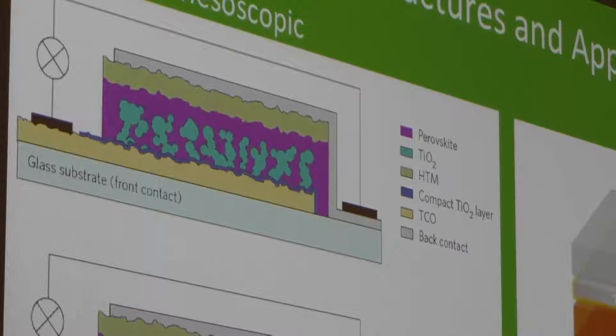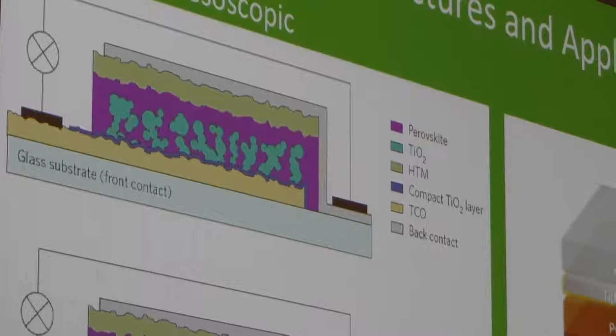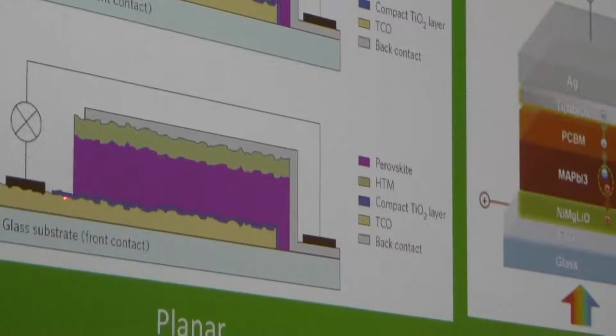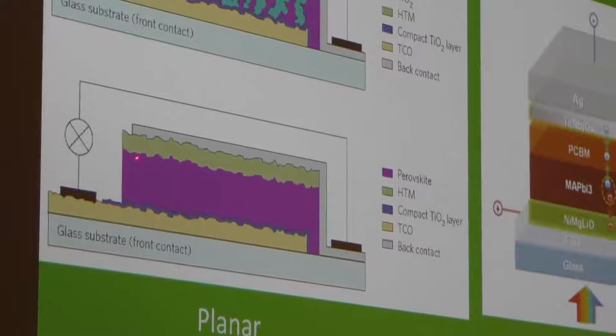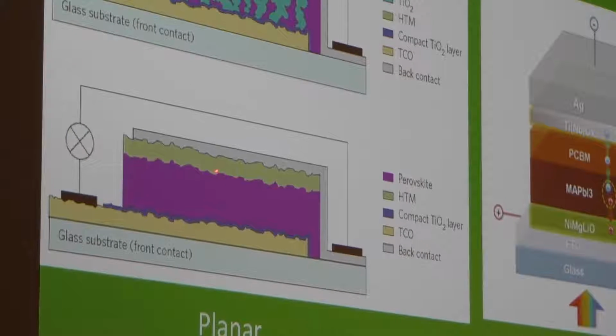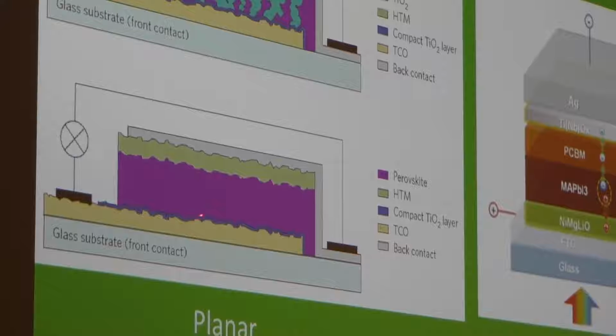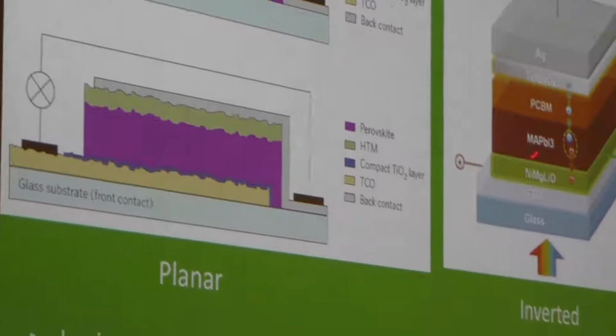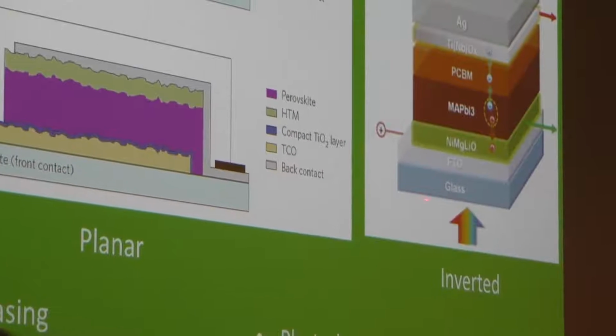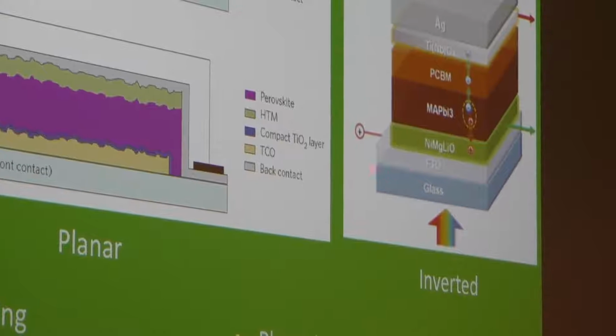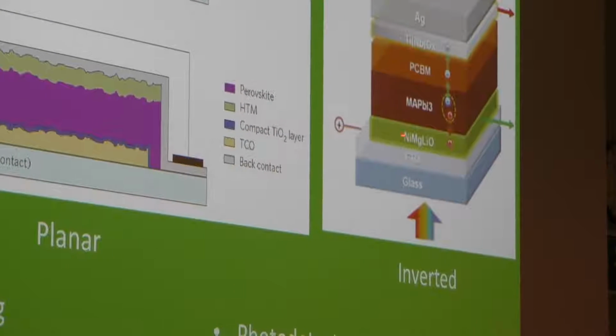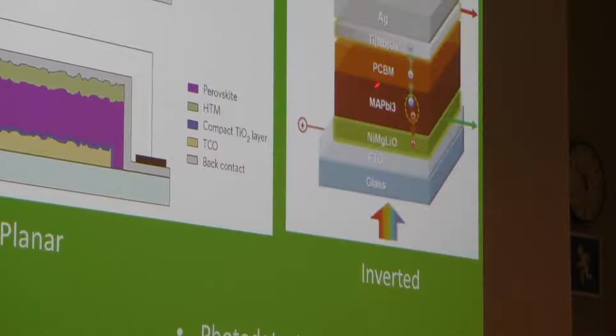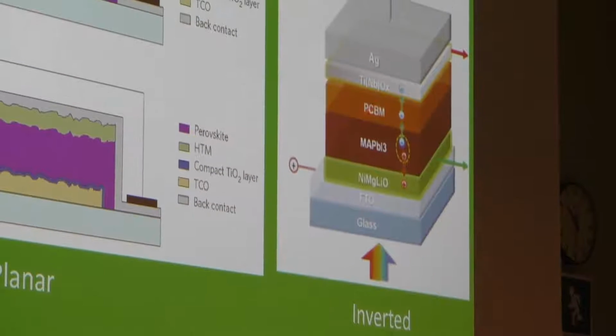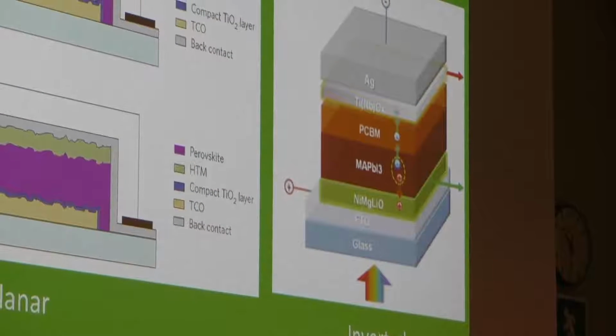You can also do it much simpler: remove the TiO2 completely and just use a thin compact layer of perovskite and hole conductor. This is what we call the planar device. If you come from OPV, polymer solar cells, you tend to start with the hole transporting layer instead. This can be nickel oxide, perovskite, and then an electron collector on the top like this. We call that the inverted structure.